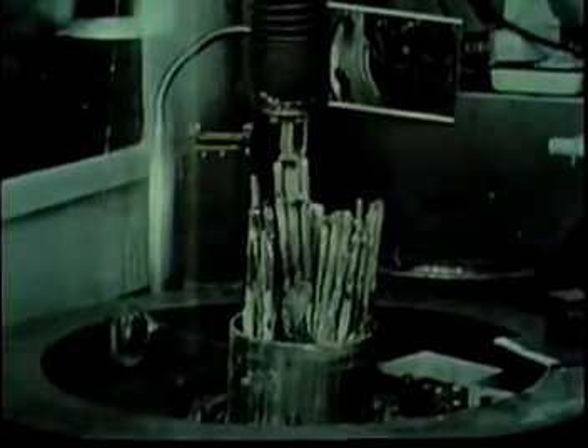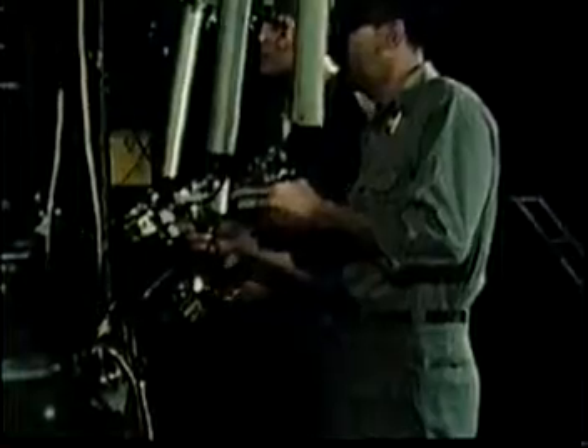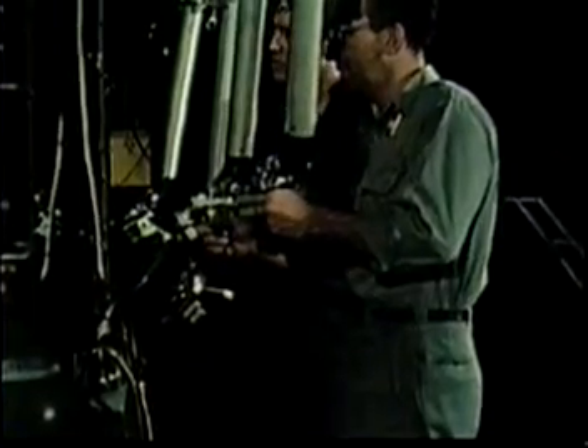It was observed that the molten fuel alloy had moved upward approximately five inches between the upper blanket rods. As nearly as could be determined by observation, no evidence could be seen of the unenriched blanket slugs being damaged by melting. Complete rods could occasionally be removed from the outer part of the core assembly. The jackets on these outer rods showed damage from the molten fuel alloy which had surrounded them, but the fuel slugs within the jackets were usually undamaged.